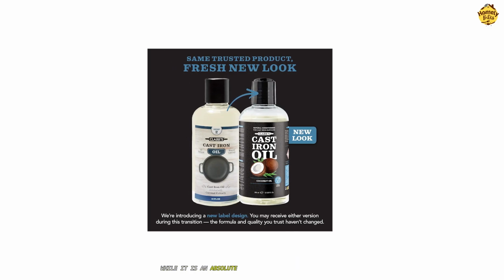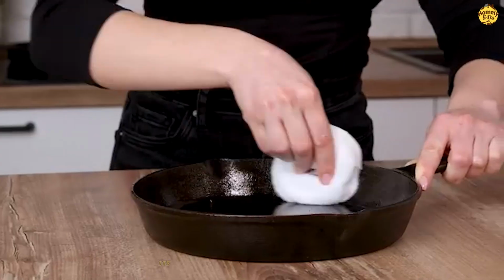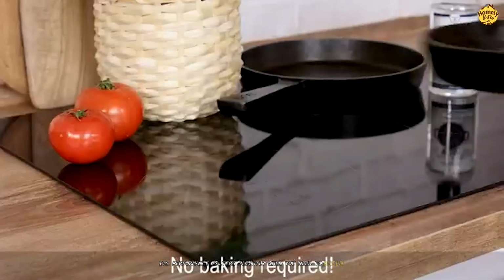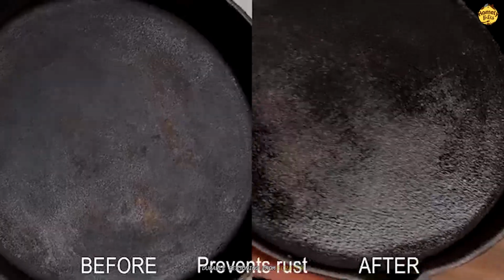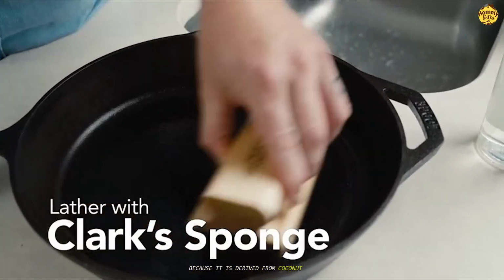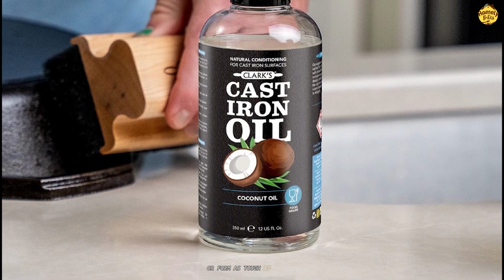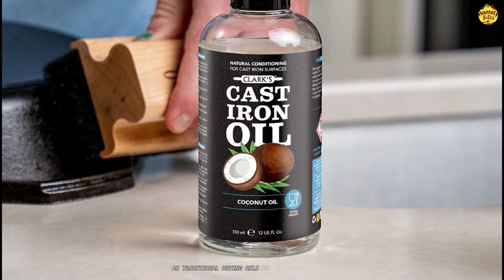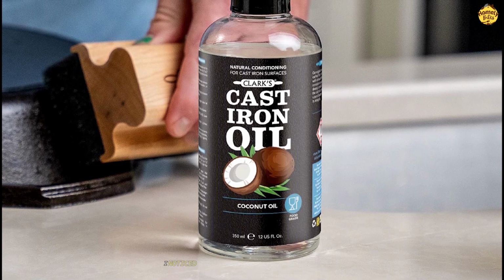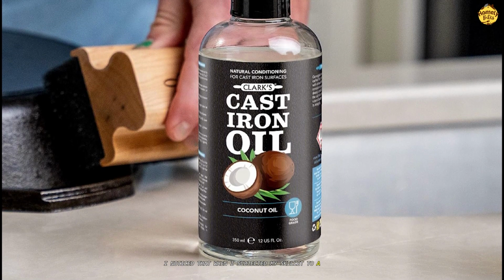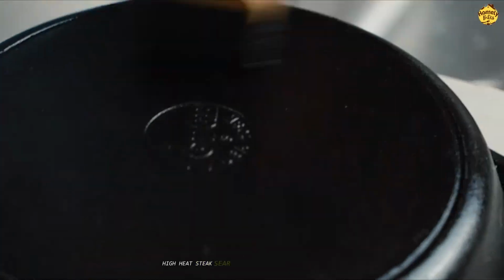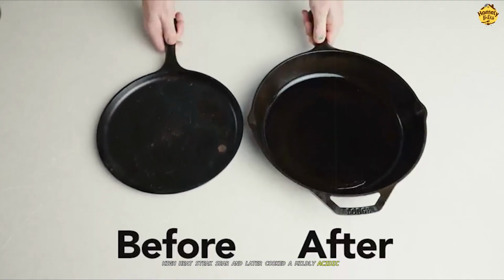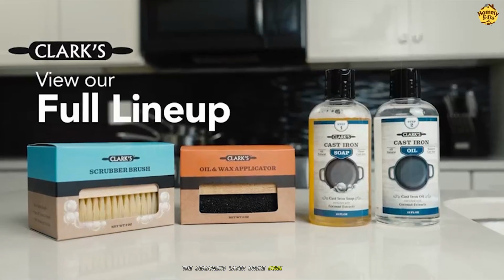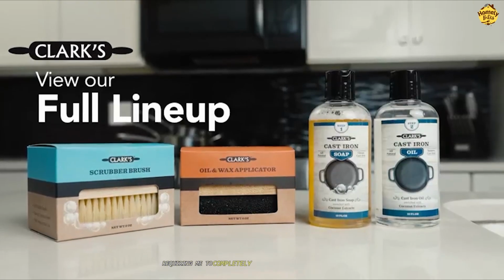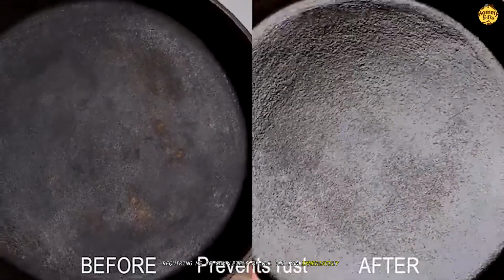While it is an absolute joy to use for simple hydration, its performance falters slightly when you need to build a hard, durable seasoning from scratch. Because it is derived from coconut oil, the fats simply do not polymerize as aggressively or form as tough of a shell as traditional drying oils do under extreme heat. I noticed that when I subjected my skillet to a very intense, high-heat steak sear and later cooked a mildly acidic dish, the seasoning layer broke down much faster, requiring me to completely re-oil the pan immediately after washing.